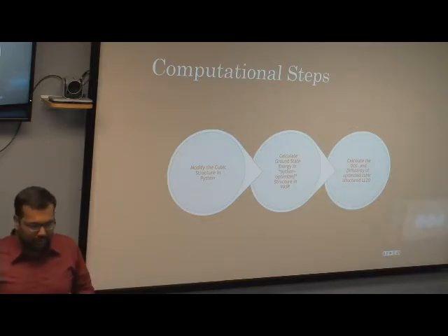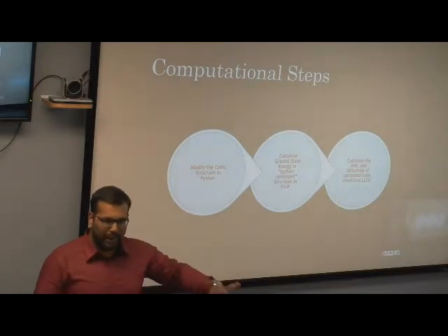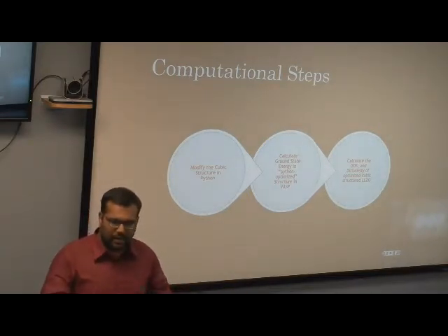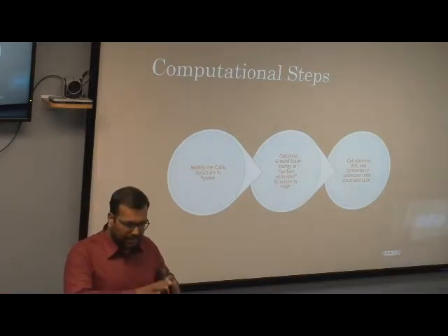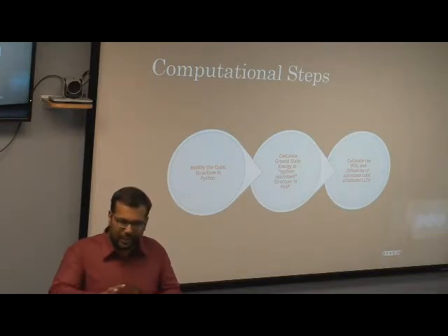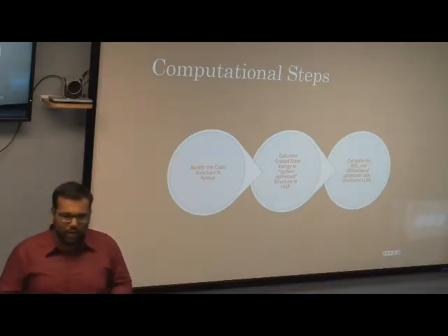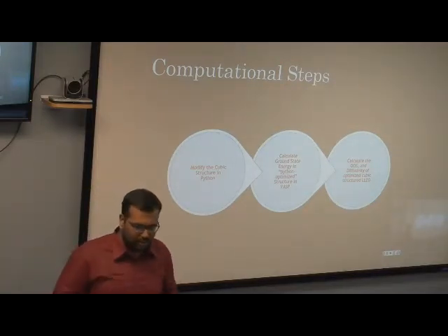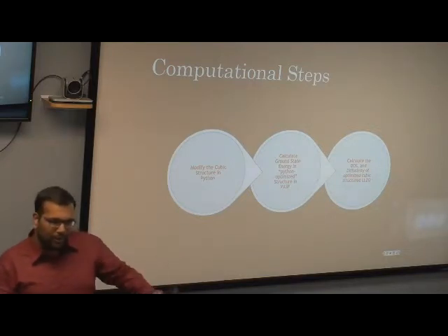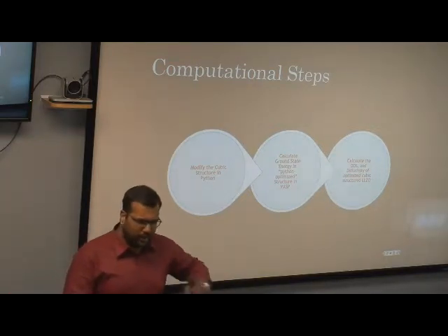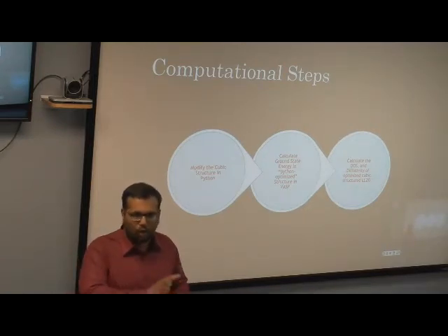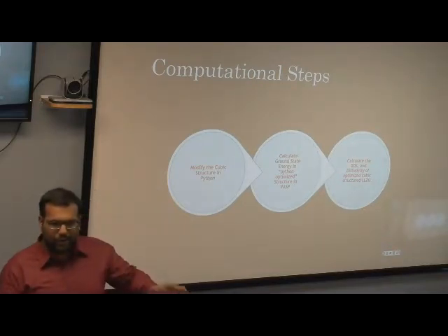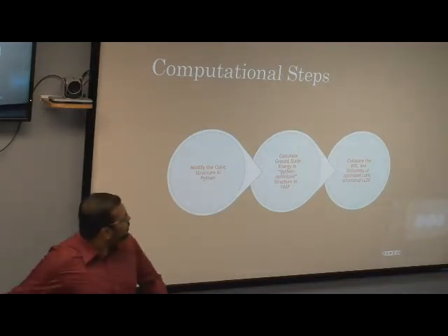For doing these calculations, I can divide my whole calculation in general into 3 different parts. In the first part, I worked in Python, where I modified the structure to remove the partial occupancy, and considered that in this cubic structure I have 56 lithium atoms in 56 different sites with occupancy 1. That means I have to remove 120 minus 56 atoms from the structure. So how will I remove them? I randomly generated around 10,000 structures, in each of which we have 56, not 120, lithium atoms.